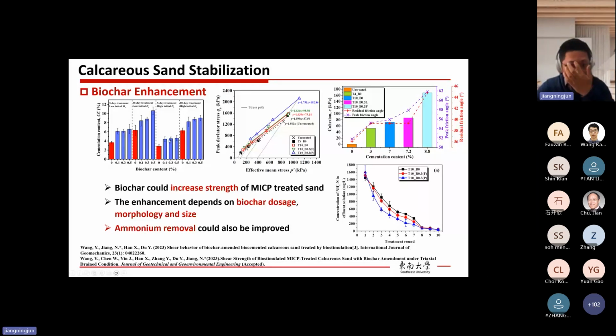Then secondly, we also did the triaxial shear test for the biochar enhanced MICP treated soil. Here you can see several lines. The blue line shows the MICP treated samples with the powder shaped biochar, and the green line shows the MICP treated samples with the needle shaped biochar. Then the red one is the MICP treated samples without biochar. If we compare these three, of course, with biochar, we have a failure envelope on the top.